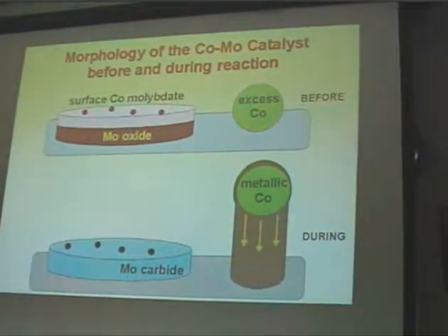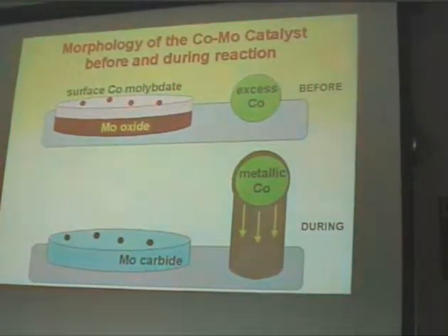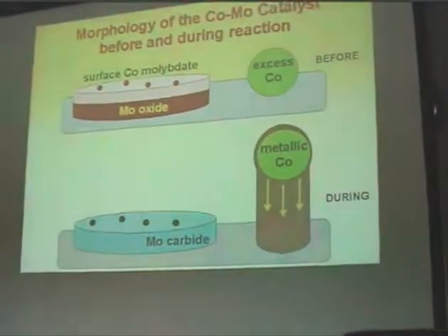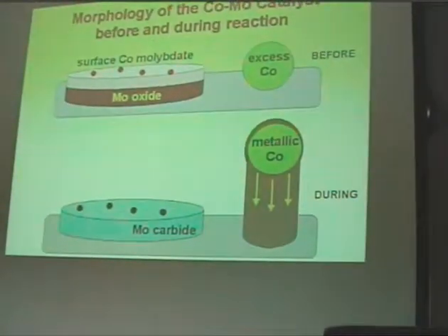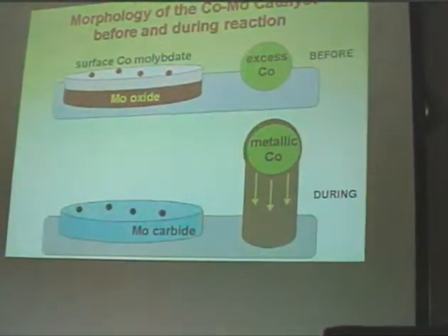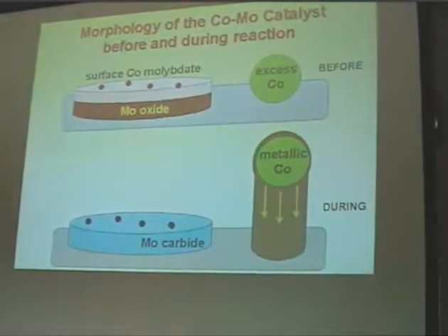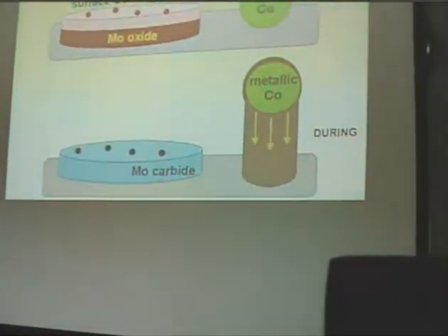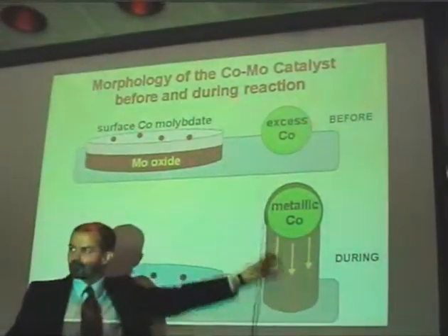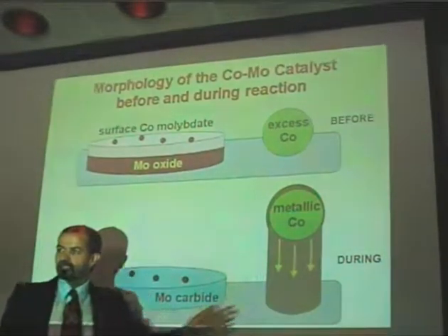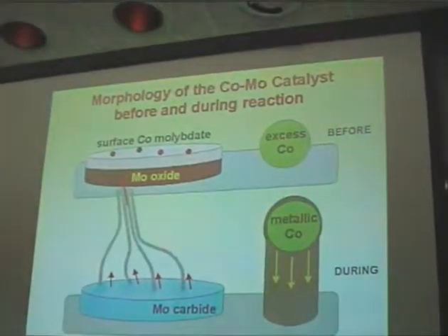So at this moment, we have this nascent, very small cluster of cobalt, which were essentially atomically dispersed in the non-reducible state. All of a sudden, they are under reaction conditions, high temperature in the presence of CO. They are ready to form nanotubes, but they are so small that they don't form these fibers of nanotubes, but rather they form the typical single-wall nanotubes.